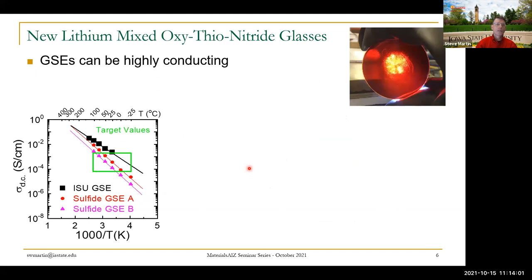Okay, but of course we know that the pure sulfide glasses have other disadvantages as well. The story I'm going to tell today is this compositional migration or walk that I've been on over the last 30 years, constantly improving these compositions to meet all the other important battery properties that you need in batteries. Well, here's the first one, this 10 to the minus three conductivity in this range of about minus 25, which we can see out here in Iowa some winters, up to about 100 degrees Celsius. So we've met the conductivity requirement.